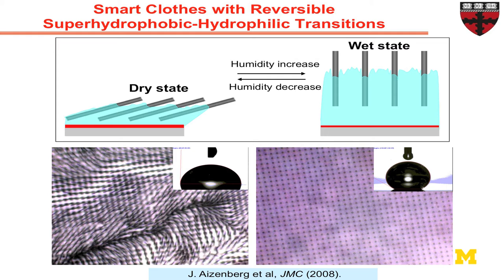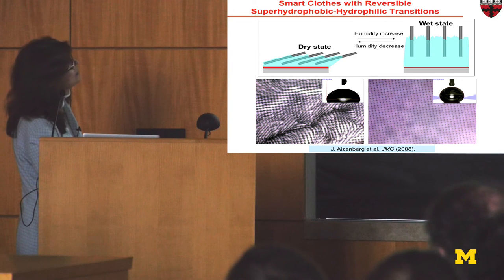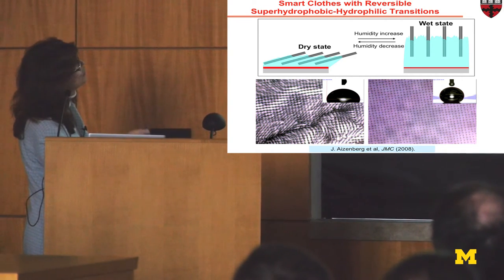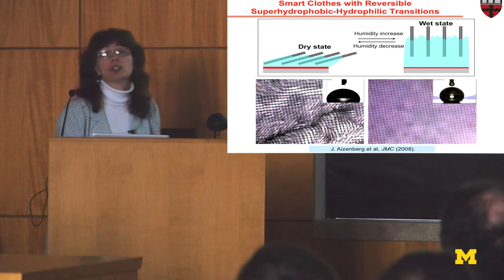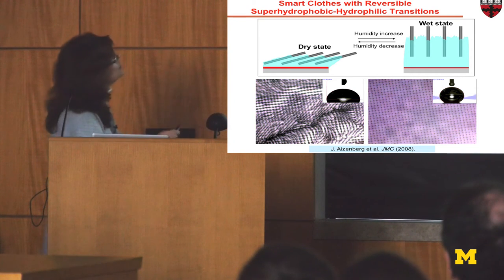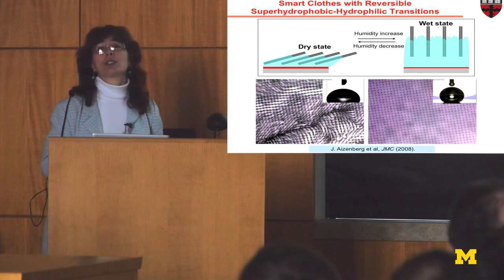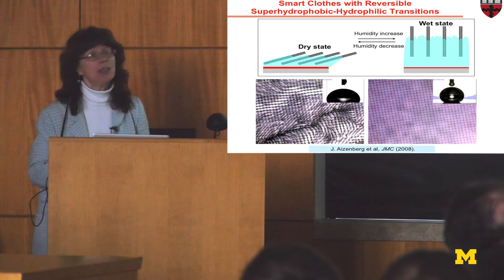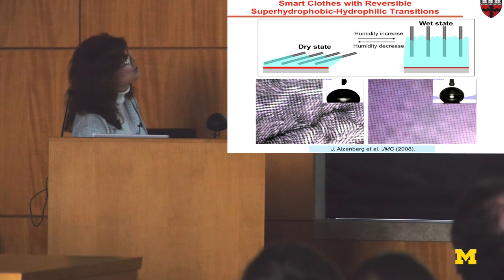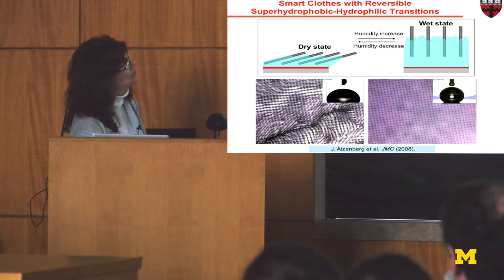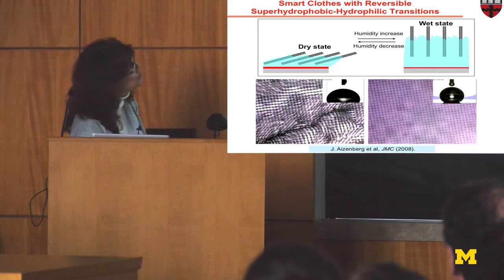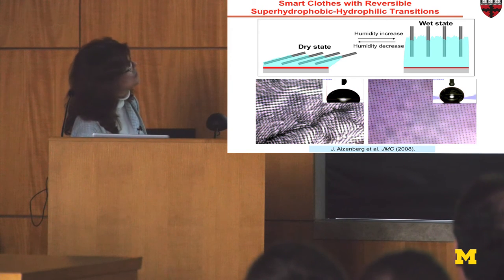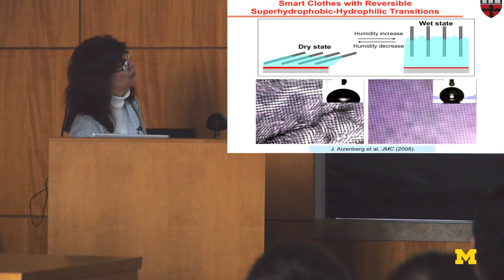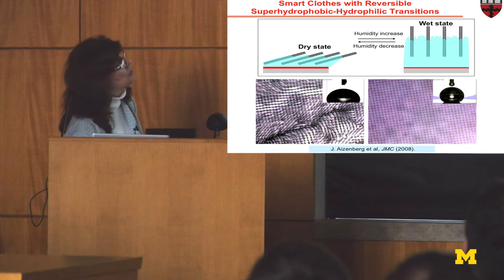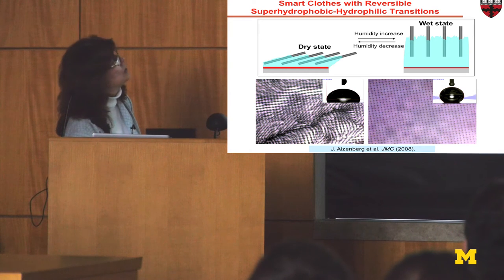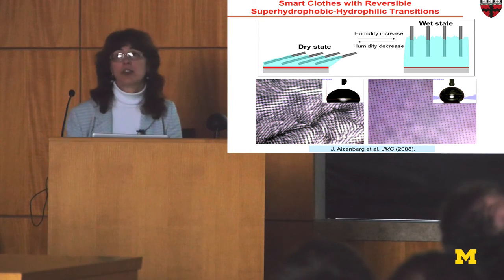On a dry day, the structures are down because the gel is contracted, and the surface is exposed mostly to hydrophilic substrate. So on a dry day, it extracts more moisture. It's hydrophilic on a dry day. However, on a rainy day, when the gel expands, only the hydrophobic part of the surface is exposed. And again, it's in response to environment. So it's a reversible surface that either works as super hydrophobic and repels moisture, repels droplets in the wet state, or becomes hydrophilic and it's reversible on the dry day.